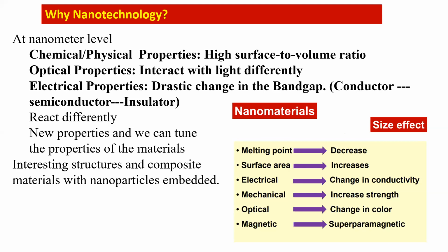Another property is the optical properties. When we go to the nanoscale, the optical properties of the material change. This is because of the tuning, or the change in the band gap, as we reduce the scale. I hope you are aware that the band gap of the material increases. Once the band gap changes, obviously all the optoelectronic properties of the material completely change. So we can generate new types of properties by using nanomaterial that are not possible in the same material when it is bulk size.